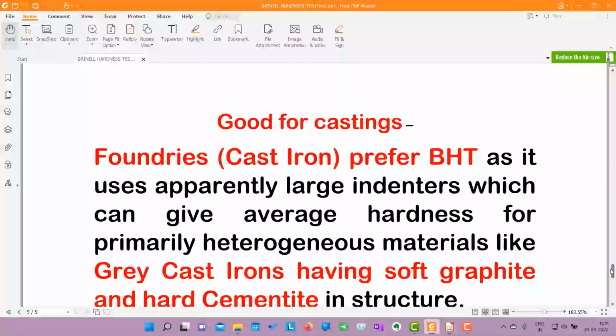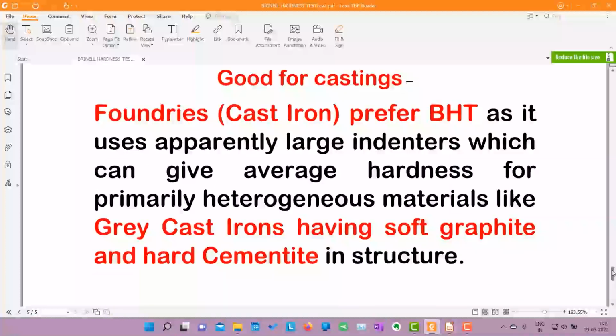Now, a word of caution. When you start the Brinell hardness testing, it is good for castings. Particularly, grey cast iron foundries prefer BHT, Brinell hardness tester, as it uses apparently large indenters which can give average hardness for primarily heterogeneous materials like grey cast irons, having very soft graphite and hard cementite. Graphite is very soft. You use graphite in pencils for writing, but cementite is very hard. So when both soft and hard phases, that is material constituents, are in the material, we can use BHN.